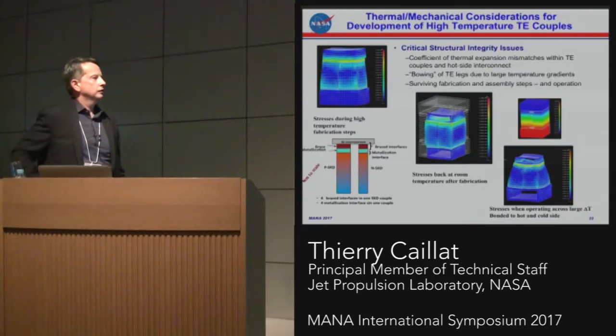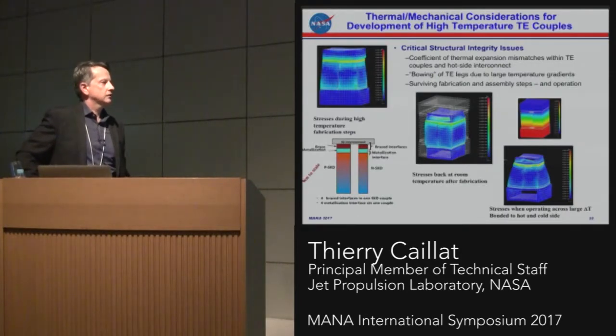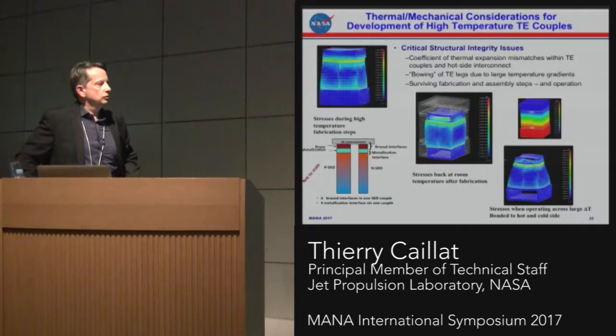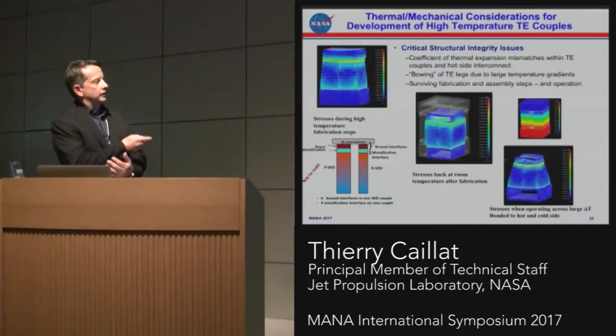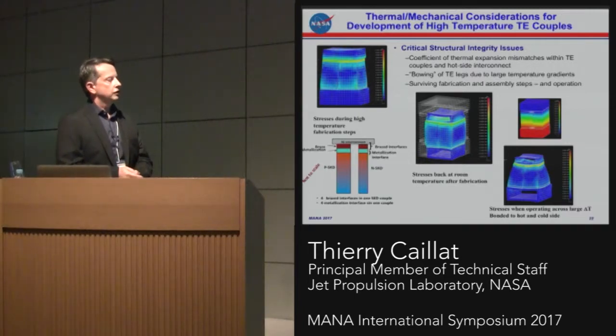That shows we are there consistently, and that's no longer an issue. So I mentioned thermomechanical stress associated with those large delta T's. That's something that we are tracking closely and doing FE analysis to understand which options in terms of metallization, interconnects, and configuration of a couple are going to yield the best stress conditions for the couples. And that has to do with, like I said, putting the materials mostly in compression, the skutterudite, not in tension, where it is much weaker.